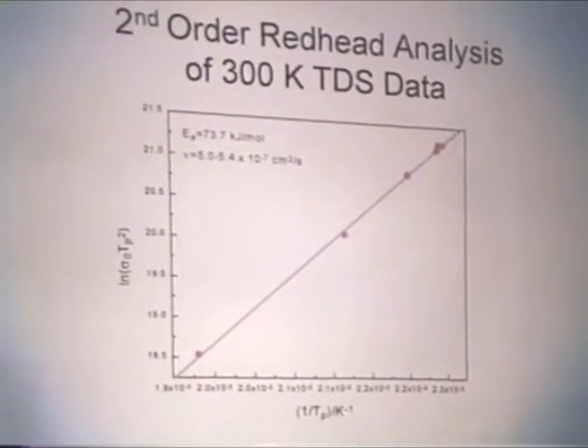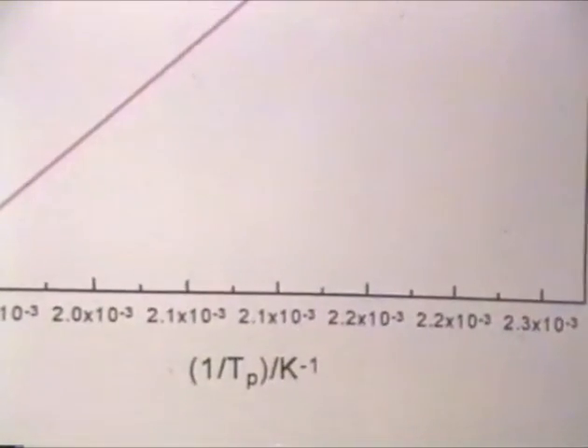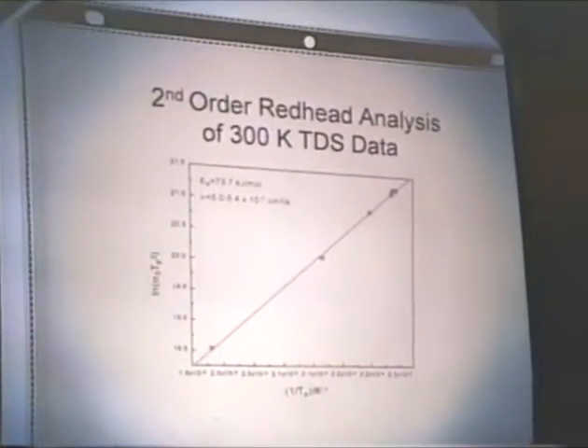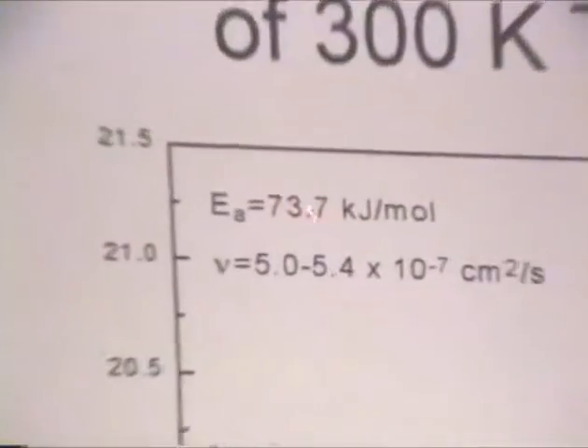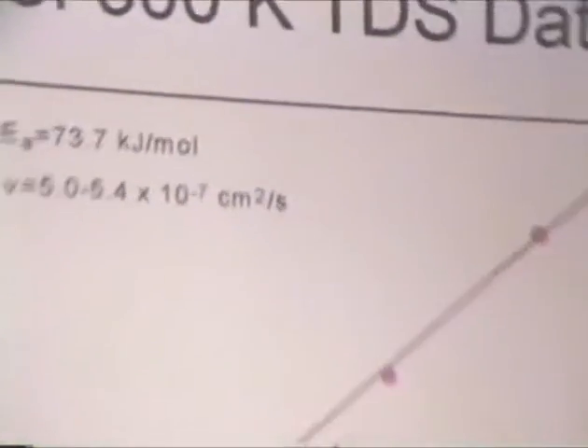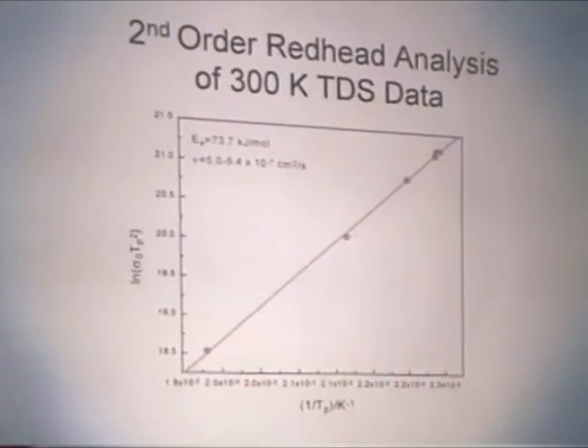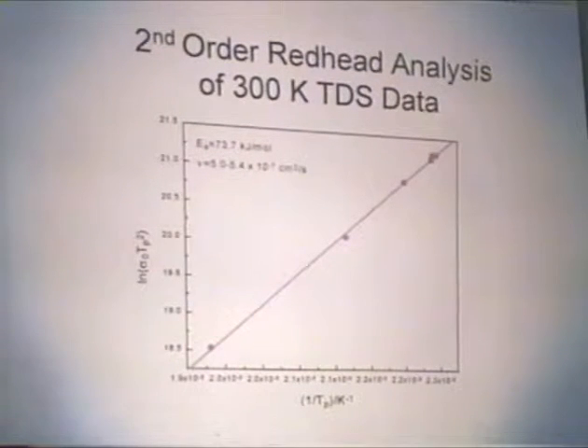So we decided to do a second-order Redhead analysis on the room temperature CO data. And of course, if you get a linear fit to your data, you should have a second order process. And we believe that's a pretty linear fit. The slope of this corresponds to an activation energy of 74 kilojoules per mole, which is close to the value that we'd expect for chemisorption. It's about 18 kilocalories per mole. And by estimating the sticking coefficient, taking an upper and lower limit, I'm able to calculate a range for the pre-exponential that varies between 5 and 5.4 times 10 to the minus 7 centimeters squared per second, which is a reasonable value for a second order process.